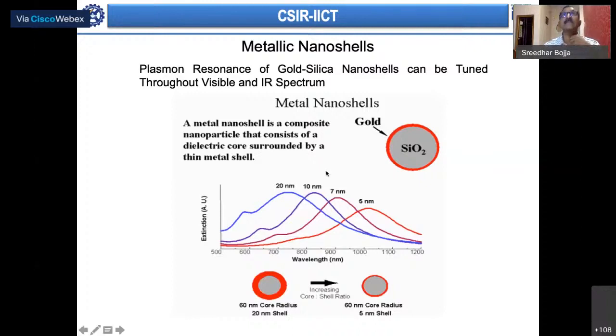But as the thickness is increased, you see that it has come down to about 750 nanometers. So depending on the thickness also, you see a shift in the surface plasmon resonance peak, and that gives us an idea about the thickness of the shell.